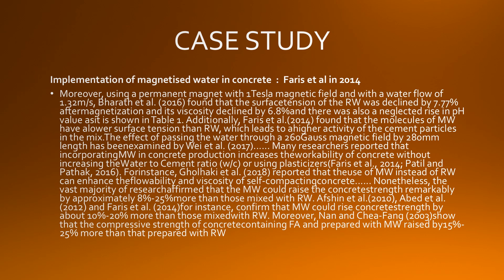In 2003, Nan and Chea-Fang showed that the compressive strength of concrete containing fly ash and prepared with magnetized water raised by 15–25% more compared with regular water.